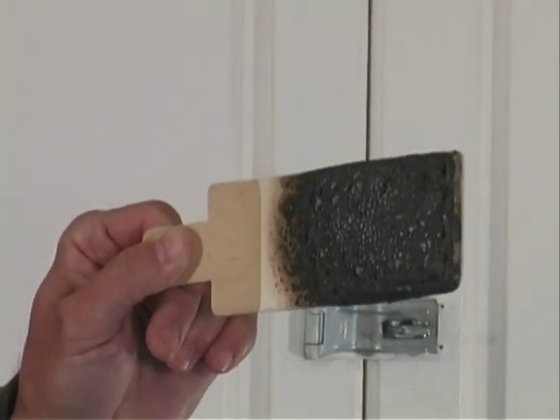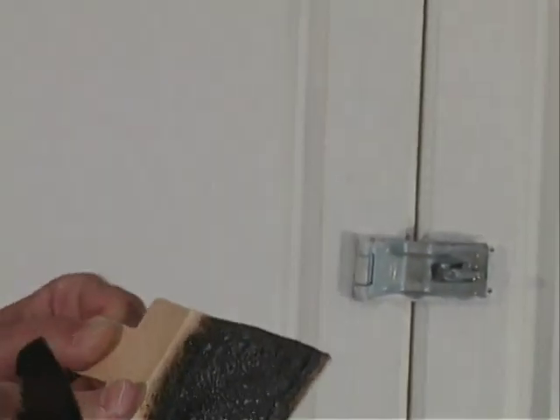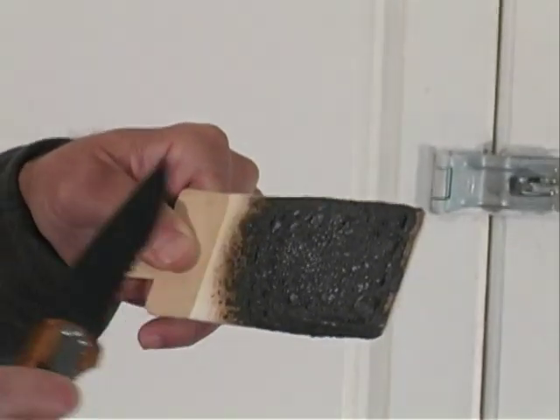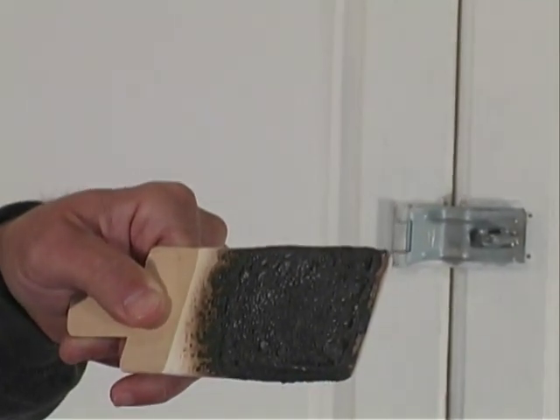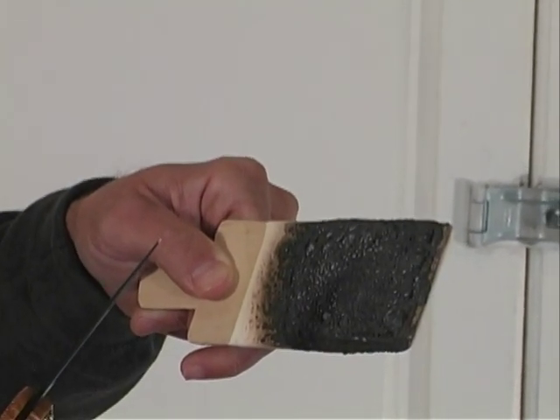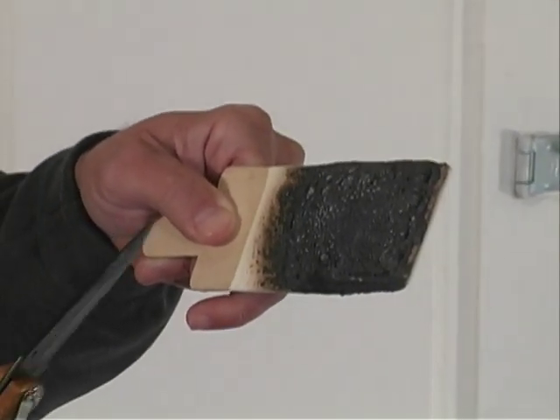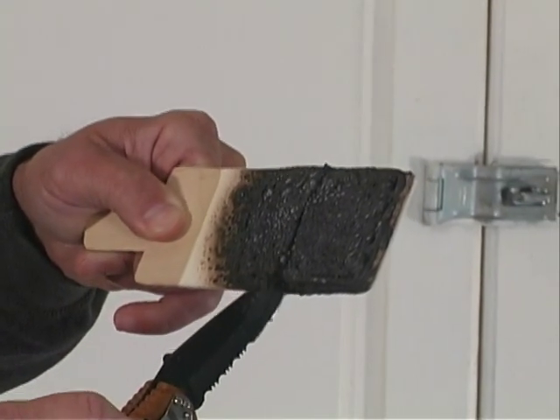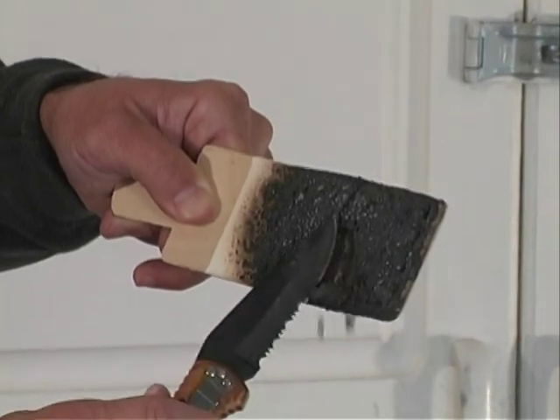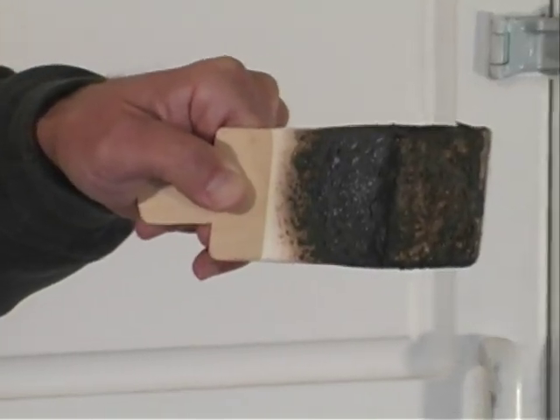Let's take a break — I'm going to turn the torch off. This gives you an idea of what the coating looks like after the fire is out. Once the fire is extinguished, I want to point out a couple of things that are really important about the Contigo coating. First of all, the char layer is dense and hard. Early generation intumescence did produce a char layer, but it was like a light cigarette ash. In a test furnace that can be useful, but in a real fire situation with tornadic eddies and things flying around, once you penetrate the char layer it loses its ability to protect. I'm going to cut through and scrape off this char layer — and notice that we still have the first layer of Contigo that was applied in place, just starting to deploy.